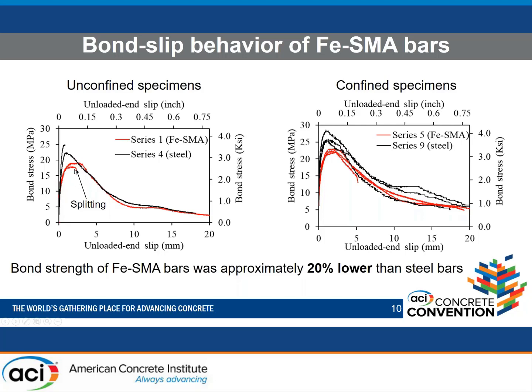And for the unconfined, one of the SMA bar specimens failed by splitting, and the other one failed by pull-out. But as you see, the maximum bond strength is very close. Apparently, this was the borderline between the splitting and the pull-out, and this observation has been already confirmed from other tests and other series that I'll present now.